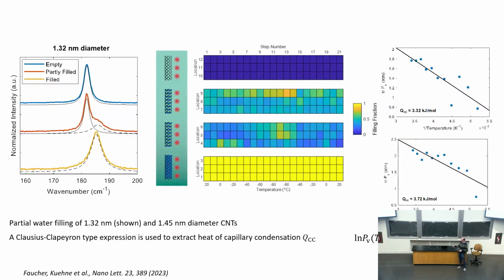Just to mention, we also observe in some cases systems where we have fractional packing, so here are partially filled CNTs. We study their thermodynamics here in terms of capillary condensation, but this is something we don't see very often. But we recently published this. Surprisingly, we found very small capillary condensation, much smaller than in the bulk.